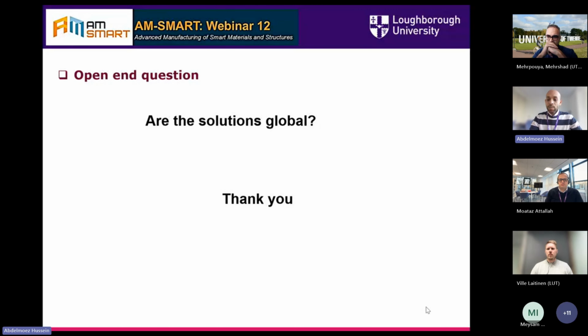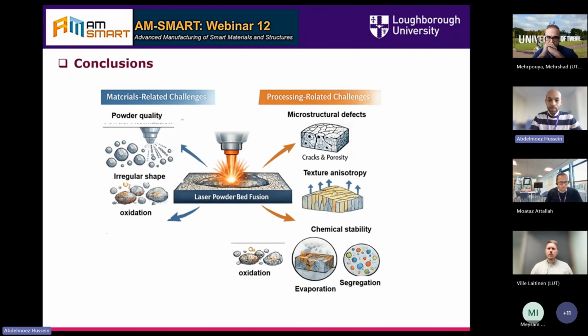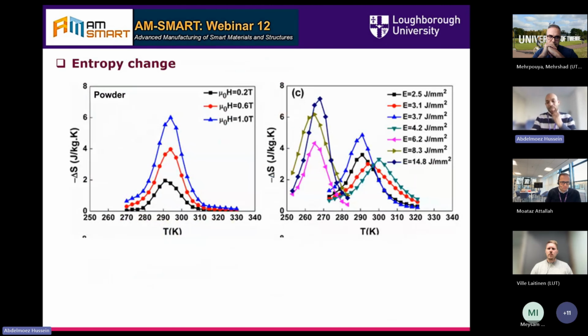Yes. For the relative cooling power, just to define it for the others, it's a multiplication between the maximum magnetic entropy change and the full width at half maximum. There are two things about the relative cooling power. The first one is that, although it has been used a lot in publications, it also receives a lot of criticism when used to compare or express the quality of a material in terms of magnetocaloric performance. This is because a material, for example, can show a delta S of 2 but have a very wide full width at half maximum. So it draws a lot of criticism. This is the first one.